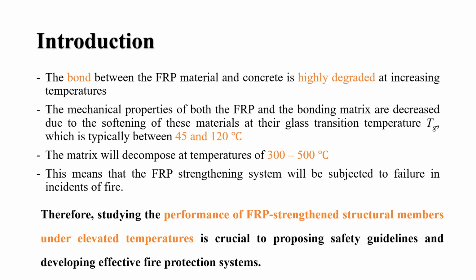For example, the bond between the FRP material and concrete is highly degraded at increasing temperatures. Also, the mechanical properties of both the FRP and the bonding matrix are decreased due to the softening of these materials at their glass transition temperature, Tg, which is typically between 45 and 120 degrees Celsius. The matrix will decompose at temperatures of 300 to 500 degrees Celsius.